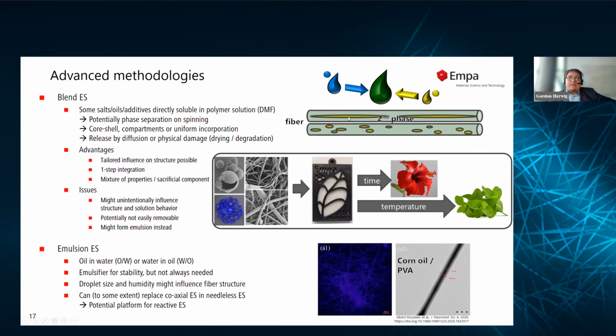When we're saying that it's forming two phases, that can already happen in solution. In this case, it would actually go into emulsion electrospinning territory. And of course, the advantage of this is that we can influence basically everything from exactly the solution that we're making. We are adding the specific components that we need to achieve either structure or composition exactly what we want. It's in one step, so there's no further post-processing unless you need it to.